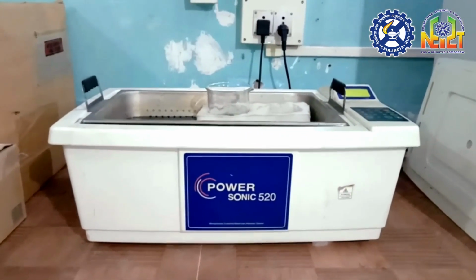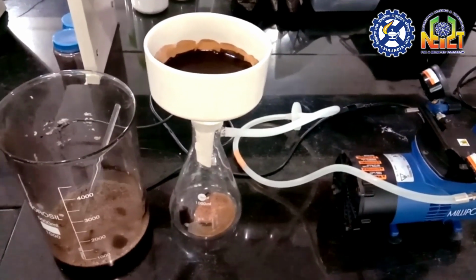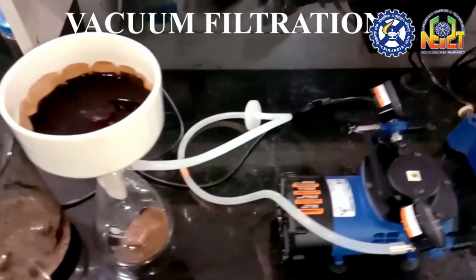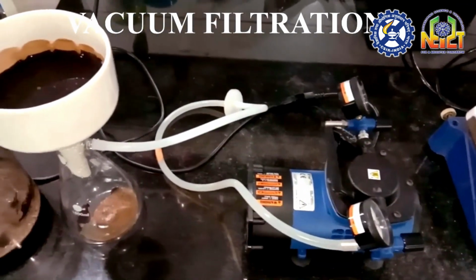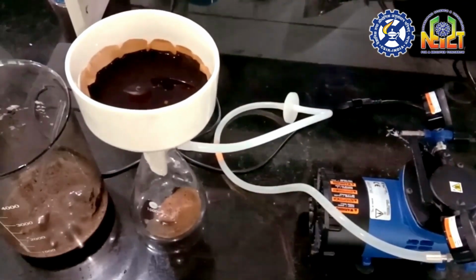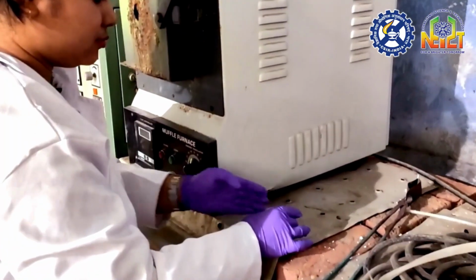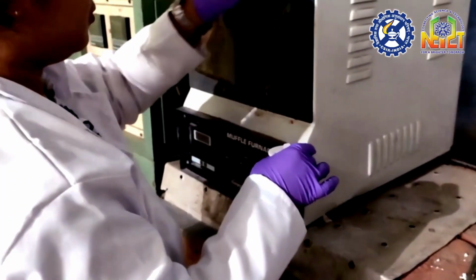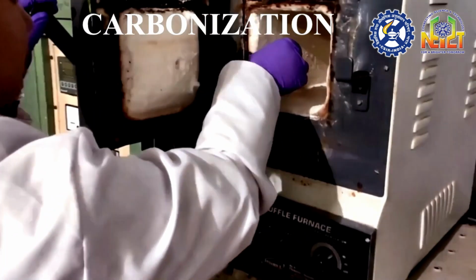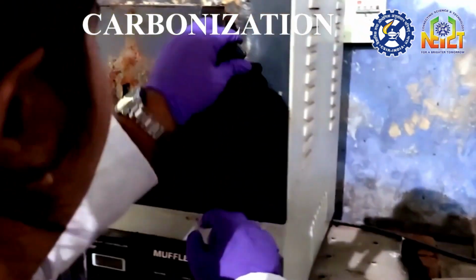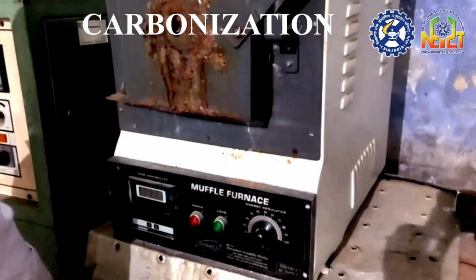For removing water-soluble, basic, and alkaline components, the reaction mixture was washed with hot deionized water until the neutralization point. The ultrasonicated coal samples were carbonized at 800 degrees Celsius for 2 hours in the absence of air.